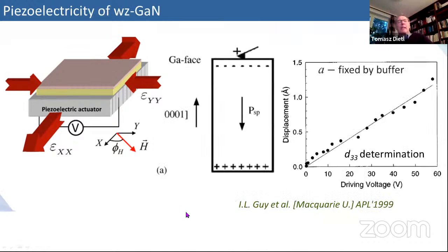So we do not need any actuator. If you apply the electric field to it, it changes. It starts to actually, for positive field here, grow and change dimensions. So we just change the C-axis, molecular beam epitaxy, substrate and buffer, fixed clamp A-axis, but the C-axis can be changed by the applied electric field.